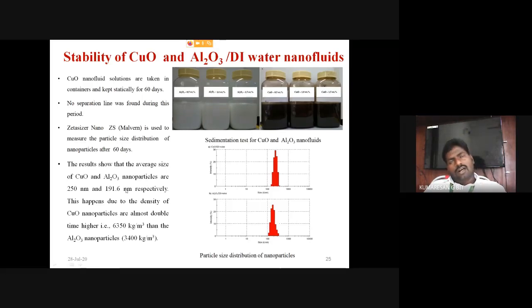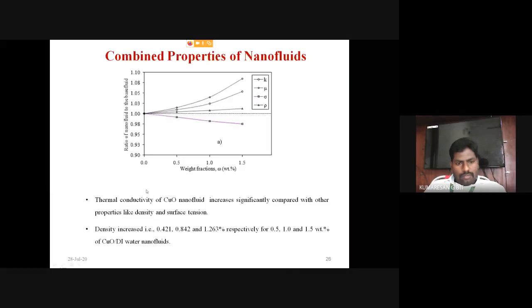So it shows that the dispersion of nanoparticles in the base fluid will not allow clustering or agglomeration of the nanoparticles. Then this graph shows the combined property analysis of the nanofluid, especially the copper oxide nanofluid. Then the thermal conductivity of the copper oxide nanofluid increases significantly compared with other properties like density and surface tension. This shows that the density and the surface tension, both properties, do not majorly influence the thermal performance of the nanofluid.